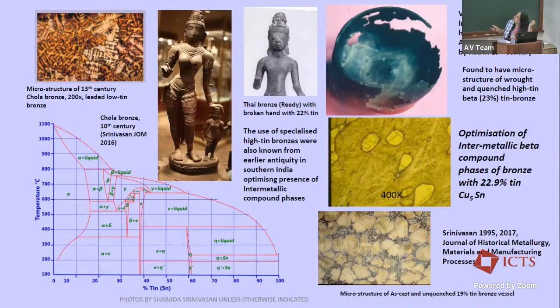And they seem to have, of course, arrived at that and extensively hot forged this bronze, which is of pure beta bronze, 23% tin bronze. And you can see that from the microstructure here. And after this very heavy degree of hot forging, they've quenched it. And that quenching is very important. Quenching means rapid cooling in water.